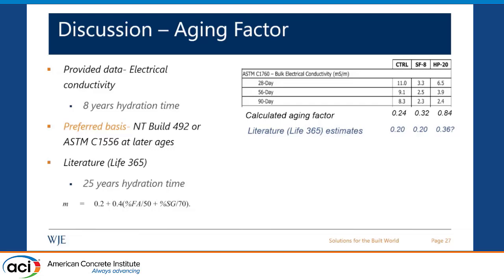So here, if we looked at the mixed designs that we are given and use the correlation given in Life 365 to estimate the aging factor, we get a lower value. And for the natural pozzolan case, it's much lower. So if we consider that this natural pozzolan performed like a fly ash, and we use that to get an aging factor based on correlation Life 365, we get 0.36, which is much lower than 0.84 suggested by the bulk electrical conductivity testing.